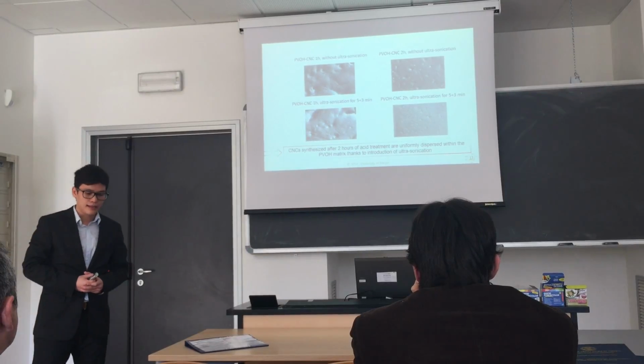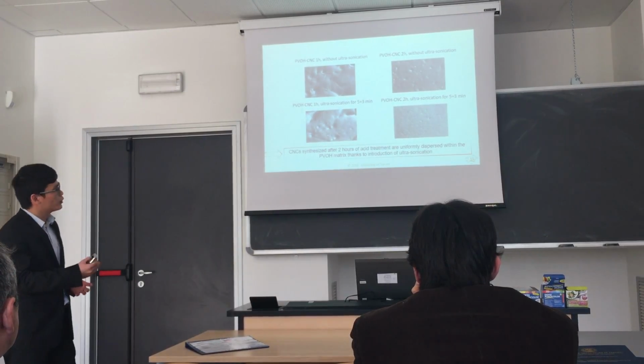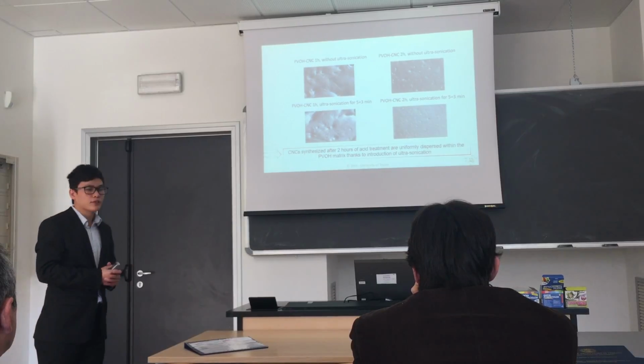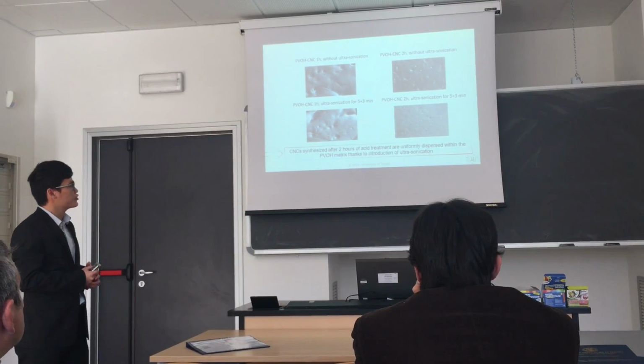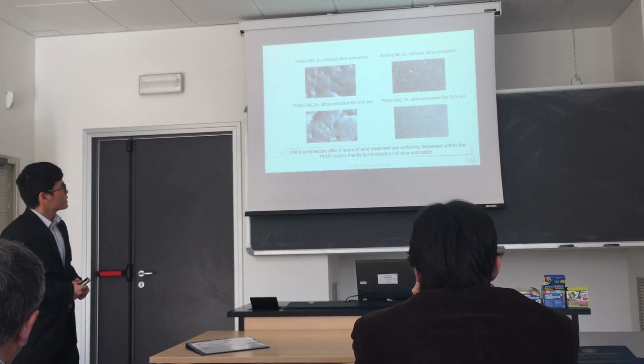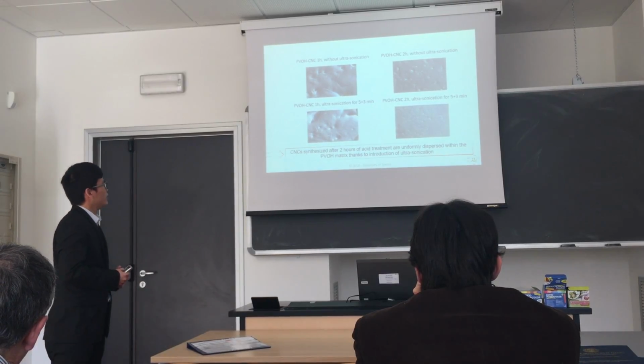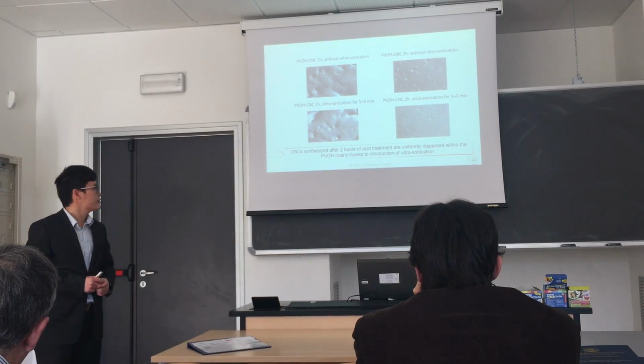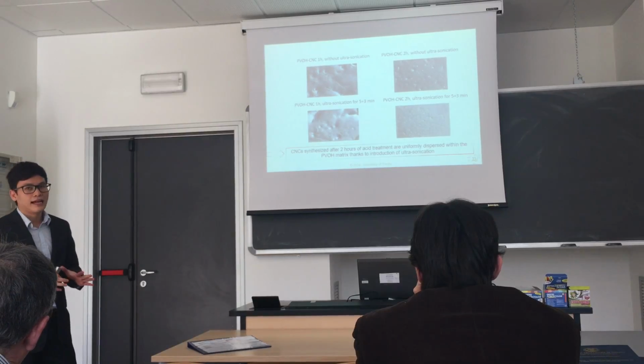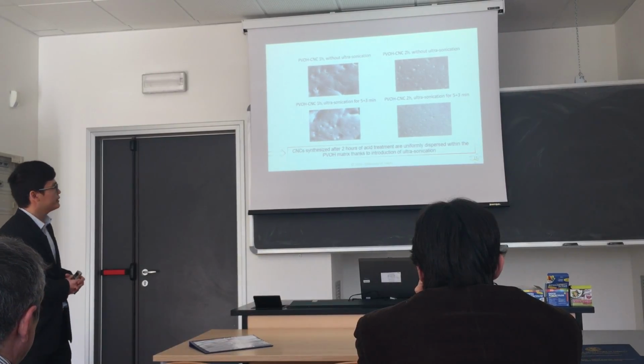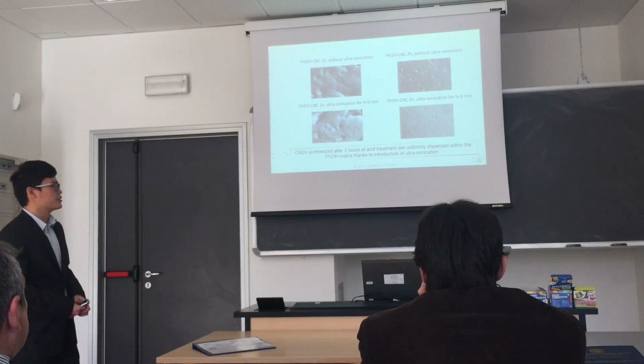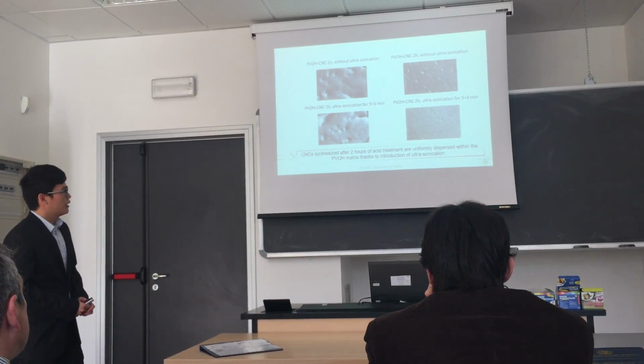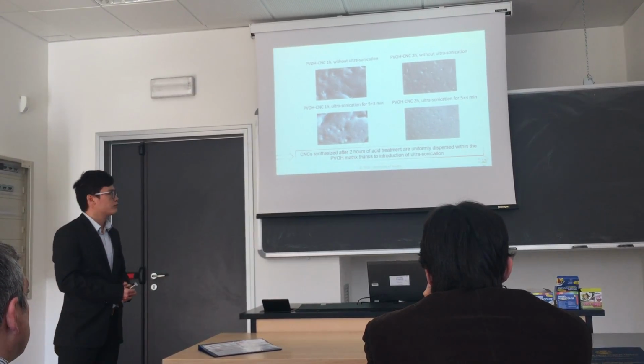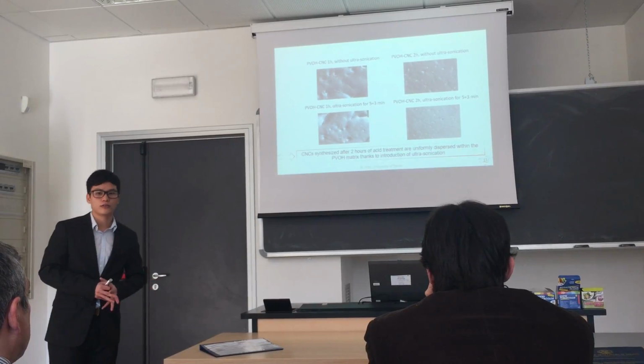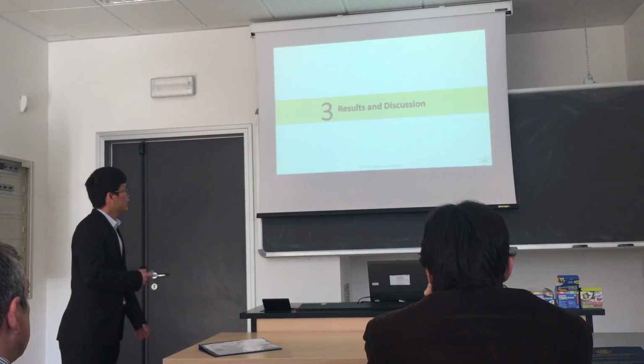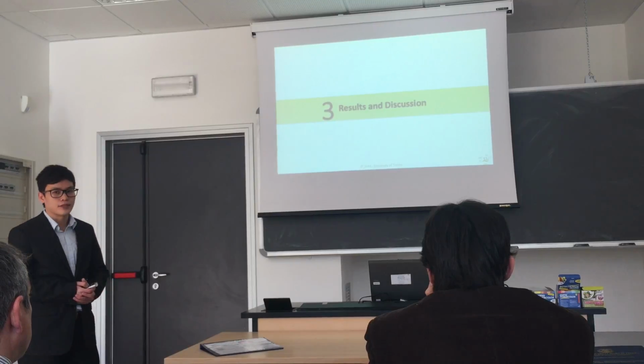This slide explains the optimal condition between the chemical acid hydrolysis treatment and ultrasonication. So from the optical microscope, we can see clearly that the CNC synthesized after 2 hours are thinner and they homogeneously disperse within the PVOH matrix thanks to the application of the ultrasonication. So we decided to choose this protocol for producing all the nanocomposite formulations. Let's move to the result discussion part.